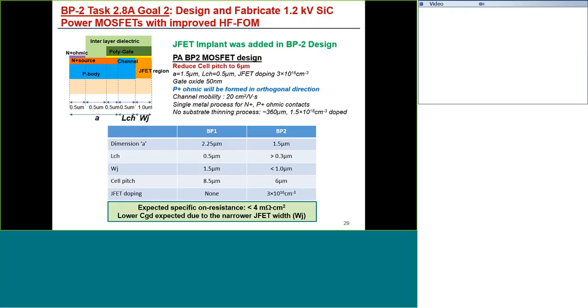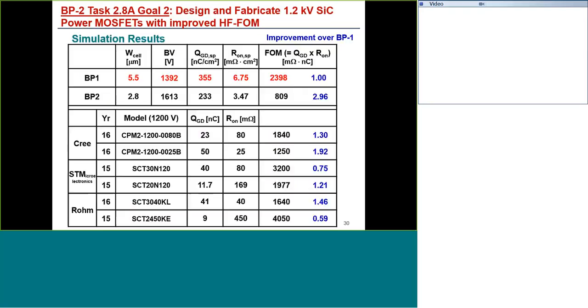And we have done another attempt to reduce our cell pitch by putting the contact to the P-body orthogonal to the cross-section. So by using these innovations, we can reduce the cell pitch down to 6 microns, which helps reduce RDS(on). And by making the width of the JFET region smaller, we can make the CGD also smaller. So these two allow us to make the figure of merit better as well.